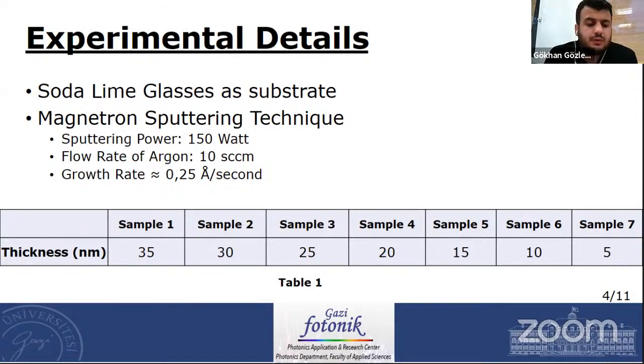Titanium dioxide thin films with thicknesses of 35, 30, 25, 20, 15, 10 and 5 nanometers were deposited on glass. Surface morphologies were examined with an atomic force microscope. Finally, transmittance results were obtained with a UV-visible spectrometer. By using transmittance data, band gap values are determined from Tauc plots.